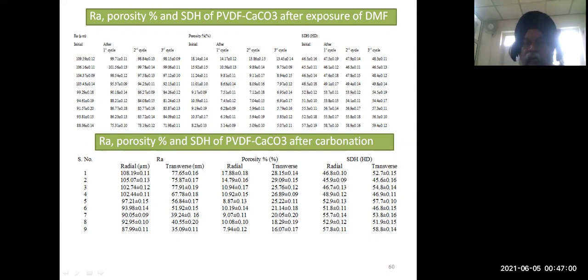Then I did the same exposure for another 10 seconds and put it in a cold chamber. There is an already established process in which people work on a maximum of 3 cycles, and it has been reported that beyond 3 cycles we are not getting a good improvement in the surface finish. Similarly, we are getting an improvement in the porosity and in the surface hardness.